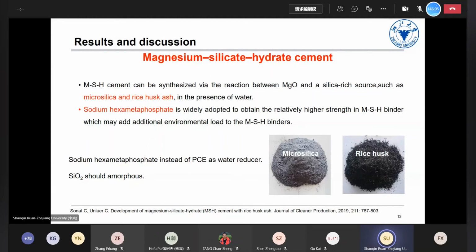And also in terms of solid waste, researchers normally use microsilica, however, some researchers also use rice husk ash as the solid waste to produce the M-S-H cement. However, this silicon dioxide should be amorphous. If it is crystalline, the strength of the M-S-H is quite low, so it may not be very effective.